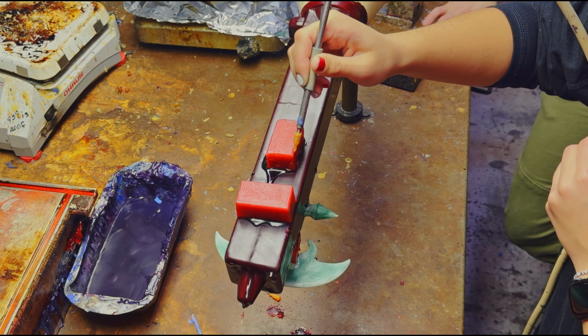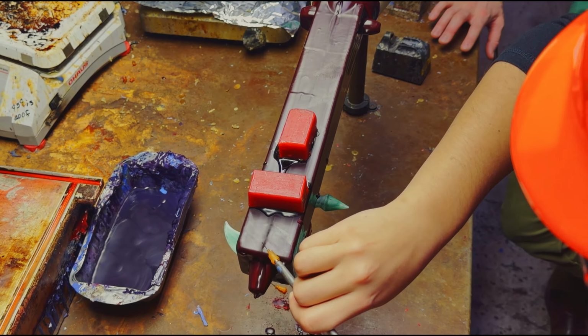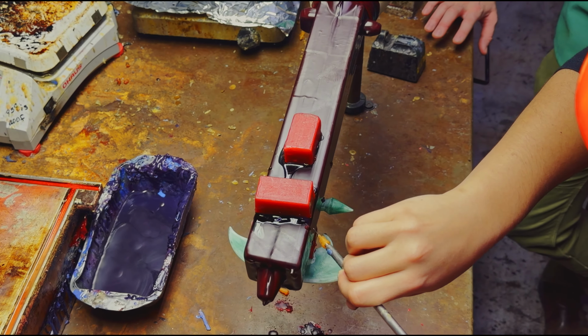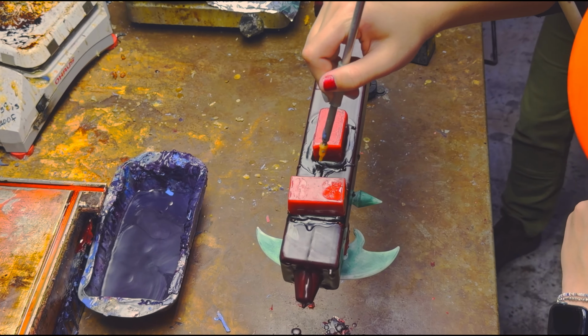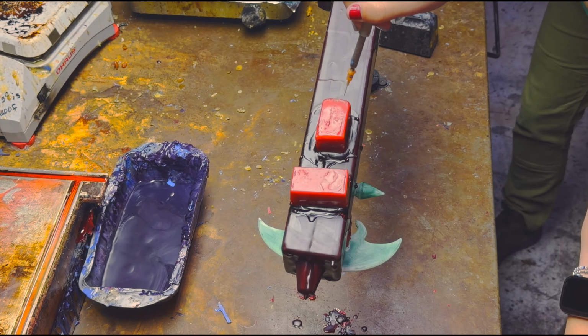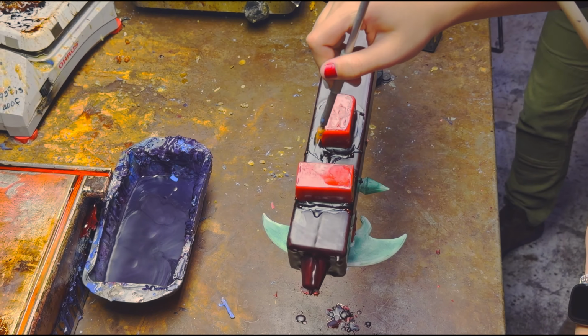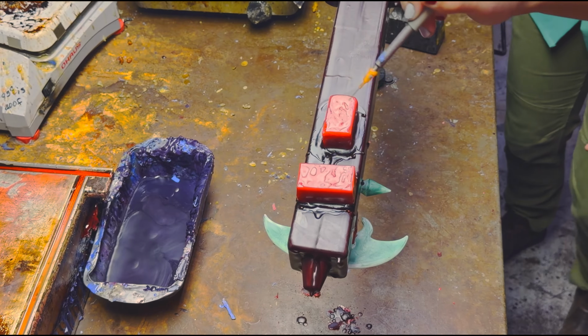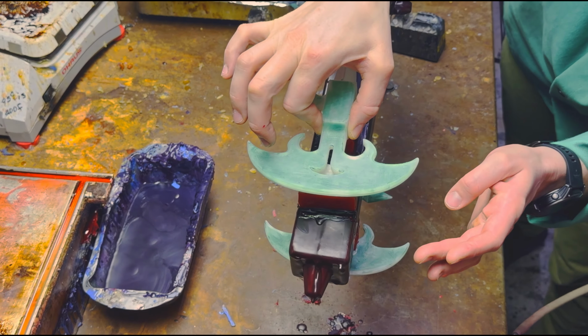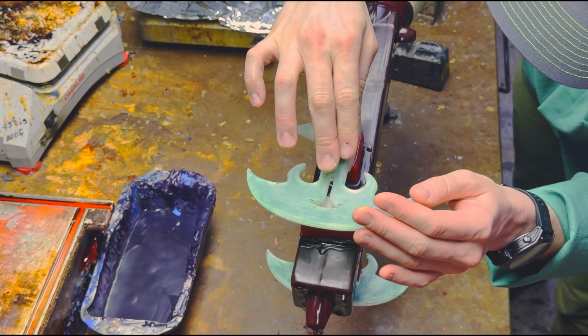By controlling the way metal enters each cavity, we reduce the likelihood of defects such as air entrapment, misruns, and cold shuts. The connection points between the part and the sprue were also designed to allow for efficient feeding during solidification, helping compensate for shrinkage and improving internal soundness.